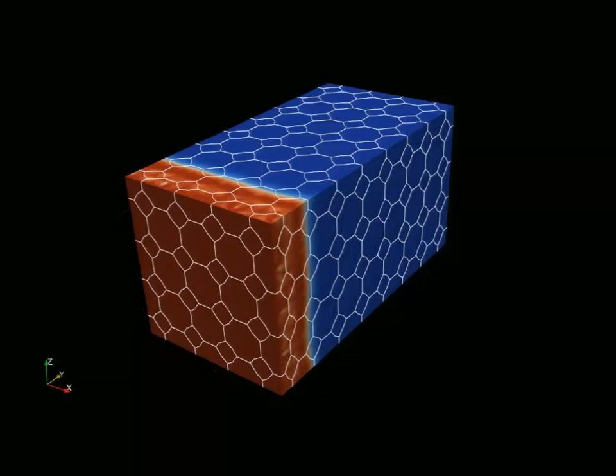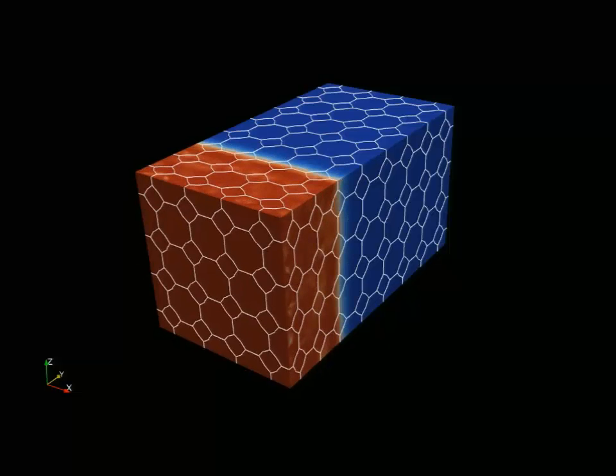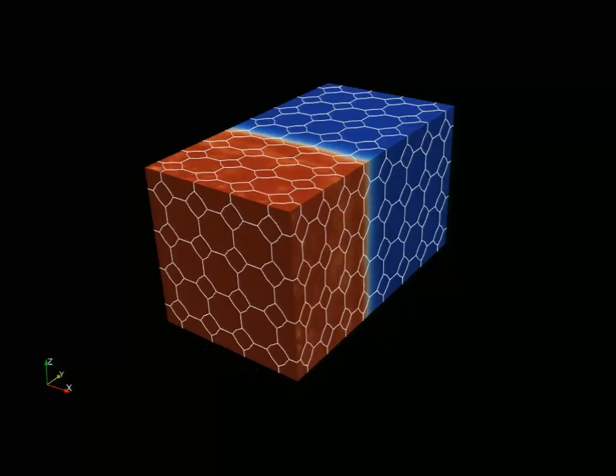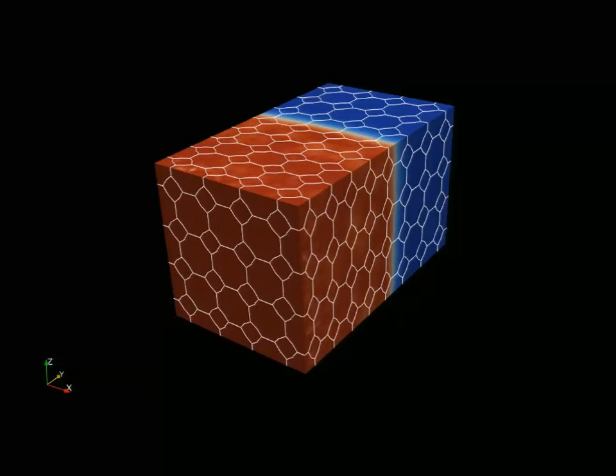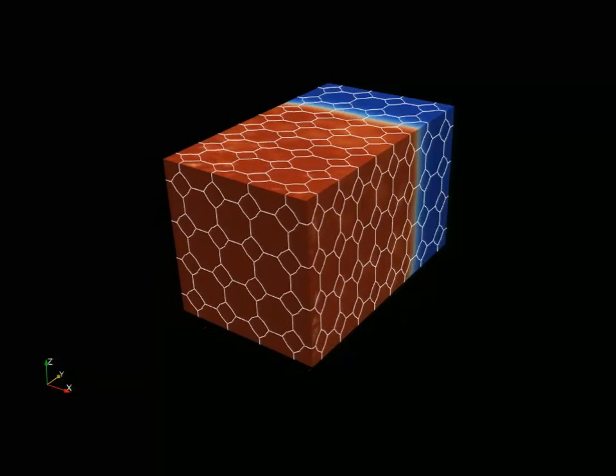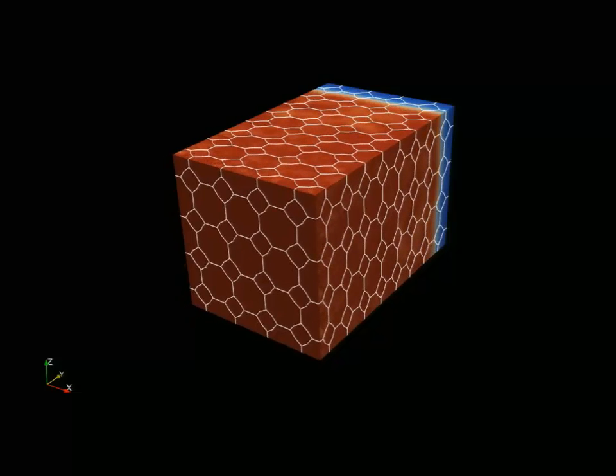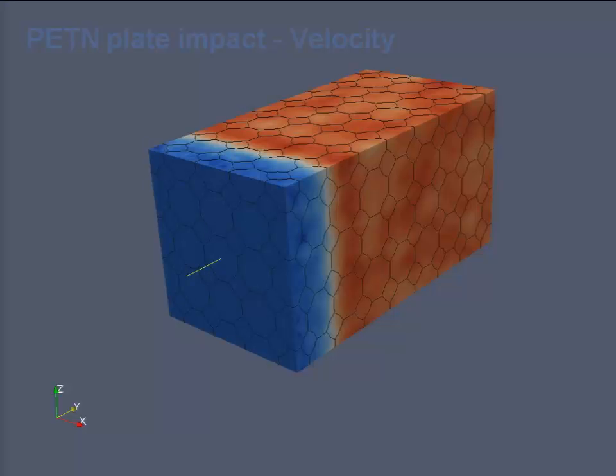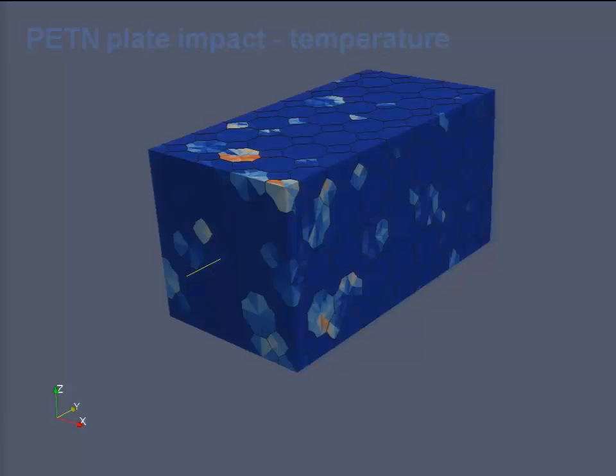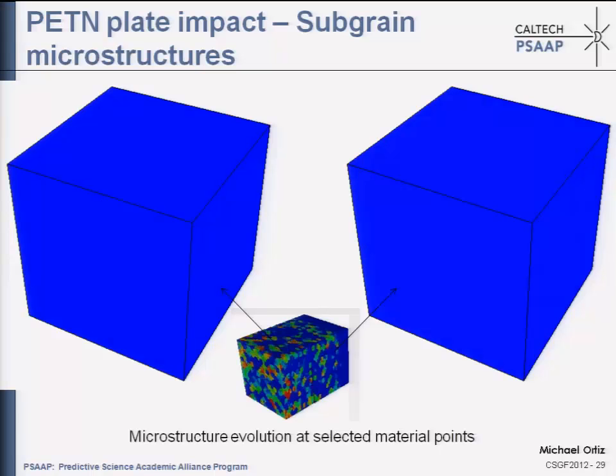So what you're seeing here is the effective model being exercised. What this effective model is giving you are average conditions. Not peaks, but average conditions. So you see some fluctuations here in velocity in this case, and those fluctuations are due to the polycrystalline structure. So there are some fluctuations, but definitely not hot spots, something you could call a hot spot and that could be responsible for initiation. So again, this is a map of temperature. You see some fluctuations, but again, very mild fluctuations just due to the polycrystalline structure.